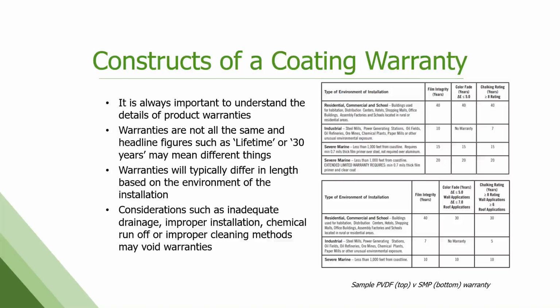But I always like to point out here that pre-painted metal, aluminum and steel for the outside of buildings, typically with a PVDF coating, is going to have anywhere from a 20 to 40-year warranty on it. And we've already talked about what an incredibly thin amount of paint that is, which is pretty remarkable given that it's expected to last as long as it does. By comparison, the typical paint warranty on an automobile, and automotive coatings are often held up as the pinnacle of paint, keep in mind, it's 5 times the thickness.